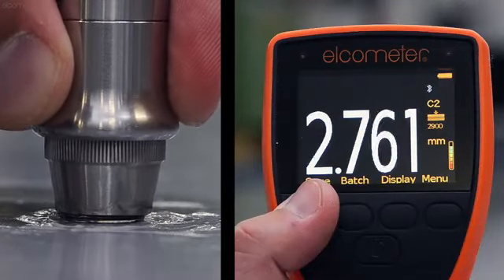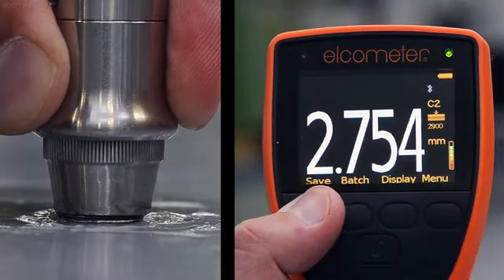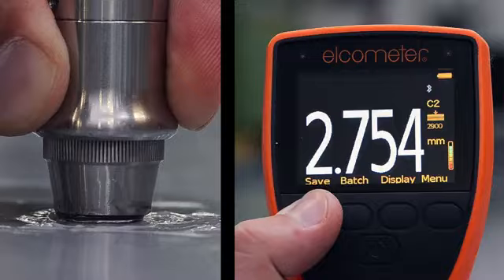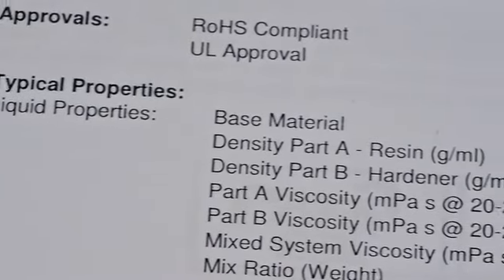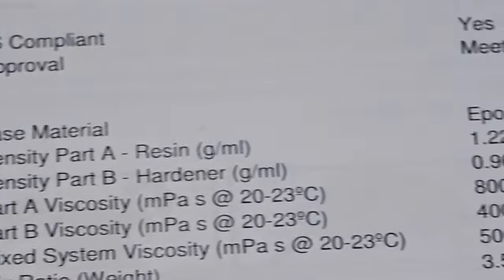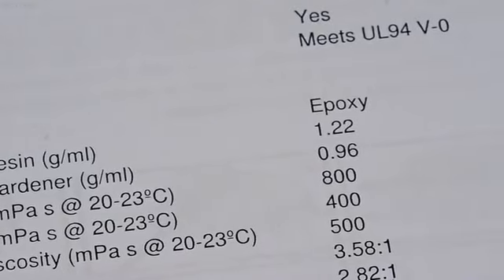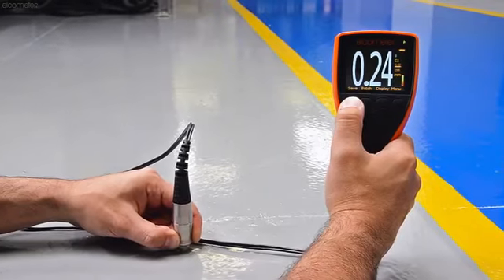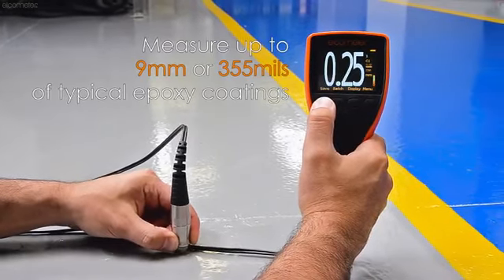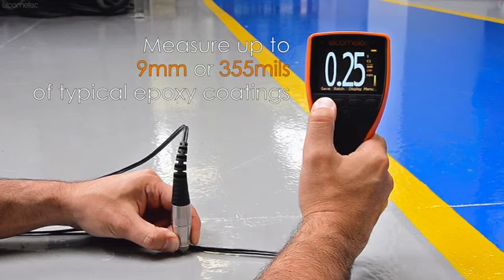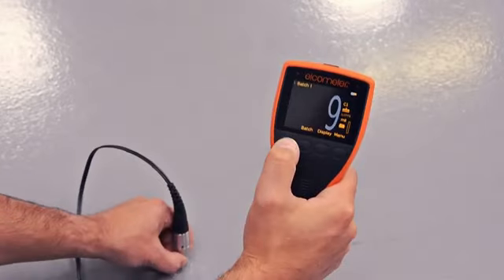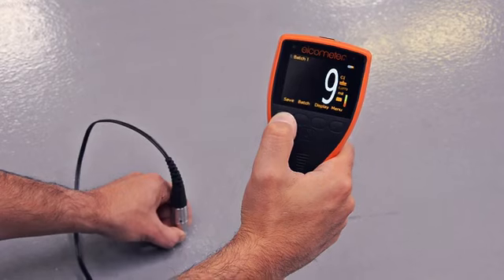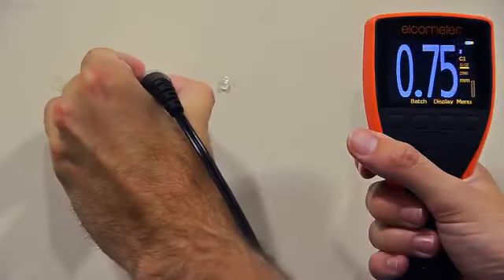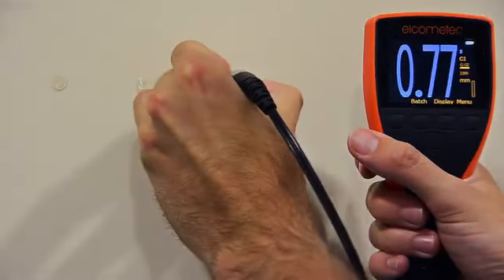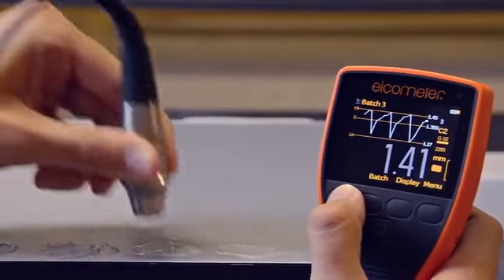As the Elcometer 500 uses ultrasonic technology to non-destructively measure the coating thickness on concrete and other similar substrates, the gauge's overall measurement range is determined by the coating's formulation. Whilst the Elcometer 500 can measure up to 9mm or 355mils of a typical epoxy coating, more sound-absorbent coatings such as rubber will reduce the measurement range of the gauge. Similarly, due to the nature of the measurement technology, coatings with high levels of aggregate may also affect the performance of the gauge.